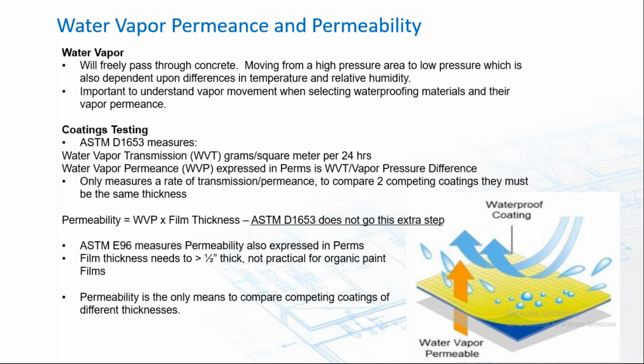Then a calculation gives you water vapor permeance, and this only measures a rate of transmission or permeance. So to compare 2 coatings, they really have to be of the same thickness. And the calculations within the test of ASTM D1653 doesn't actually go that far. It doesn't actually take that step to calculate permeability. ASTM E96 actually measures permeability, also expressed in perms, but a film thickness needs to be greater than ½ an inch thick, and there are all sorts of adjustments that need to be made, and at that thickness, it's really not a practical measurement for organic paint films.